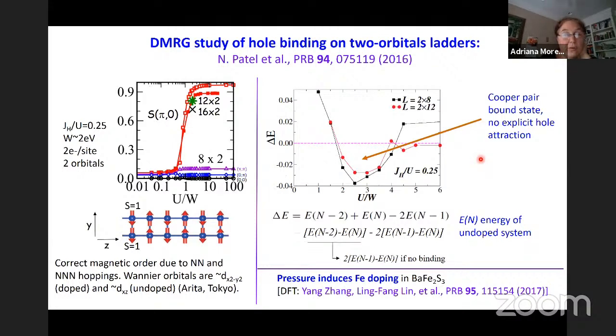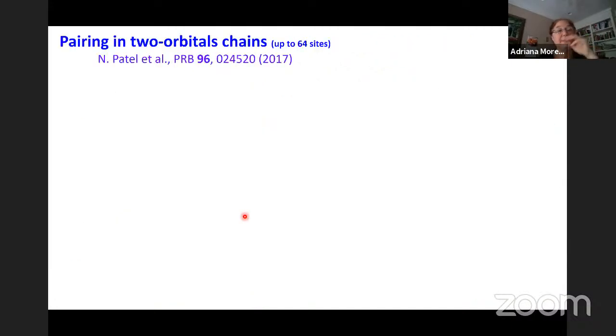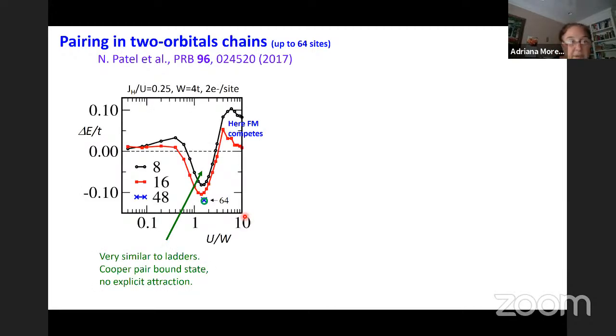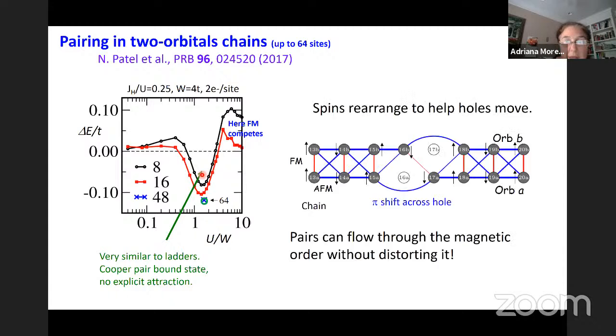These results were for the ladder with two orbitals. So now we decided to look at chains in order to go to larger systems. These are results for two orbitals in a chain, and again we observe pairing at intermediate values of U. At large values of U, the pairing is even worse than in the ladder.